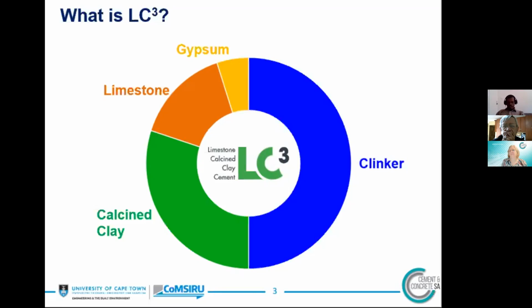But depending on the required performance of the mix, you can even go down to 40% clinker. And you don't need high-grade carbonate clay. A clay with about 40% carbonate content is usually enough. So in general, proper preparation and optimization of these constituent materials is important. Otherwise, you may end up having a system with poorer performance than the conventional systems.